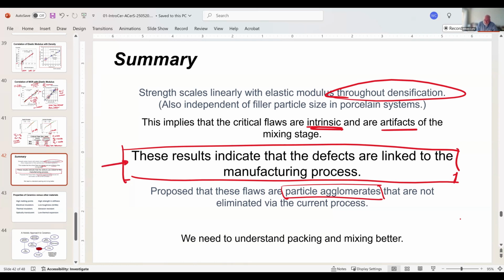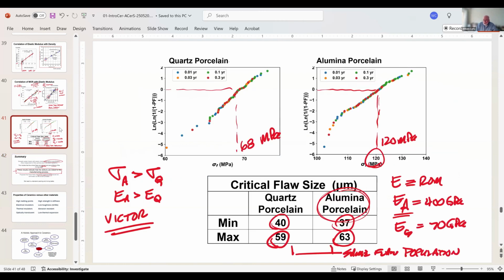This is important because, and by the way, I didn't go through this slide very well, but I will in a minute, it says that if our process is in control, we will always have the same flaw population. These plots here are Weibull plots. They're actually called two-parameter Weibull plots of the data. I want to show you a couple things that I glossed over. There are 4 sets of data here, with roughly 100 test specimens in general.